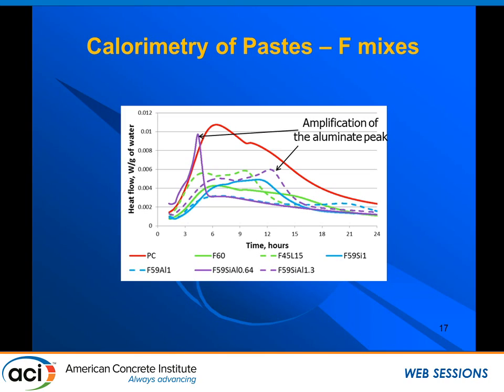When we put in the 0.64 silica to alumina ratio, we have a significant change in the curve. First, it shifts to the left and matches the PC mix. Second, the aluminate peak is significantly amplified, and it overlaps the silicate peak.